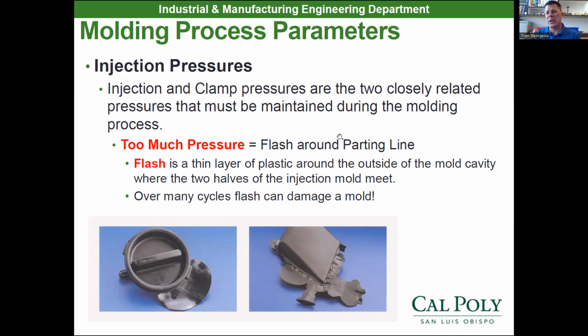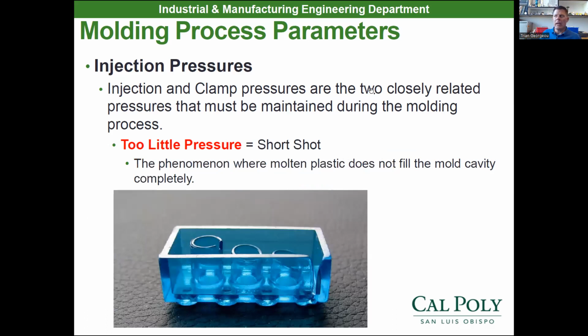So that's why we also have to control our injection and our clamping pressures and make sure that they're in line with each other. Now, injection pressures also cause short shots if you set them too low. So you don't want too low of an injection pressure because you can't fully fill that mold and hold while it solidifies. You can see right there, we didn't fully make a Lego brick because we didn't have enough injection pressure.